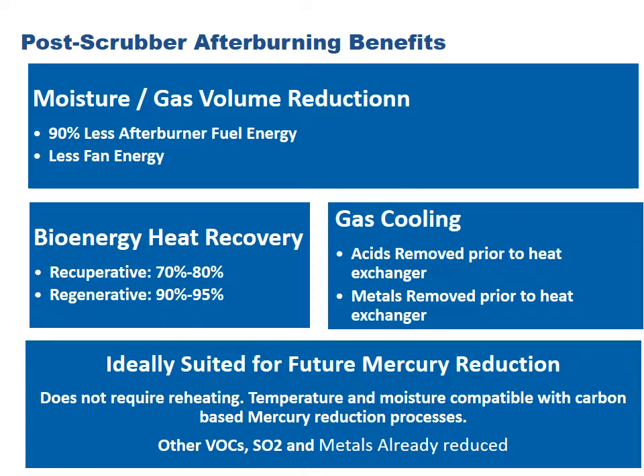The other benefits of this: like the heat exchangers for the organic Rankine cycles, this is nasty stuff, this gas. It's moisture laden, acid gases, metals, abrasives. When we go through the scrubber, we reduce all that. We condense out the acids, we remove the particulate, so now we have a relatively clean and dry gas that doesn't have near the effect on the heat exchanger that a heat exchanger located right after the furnace would.